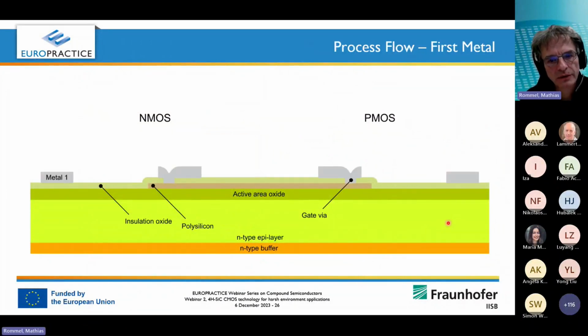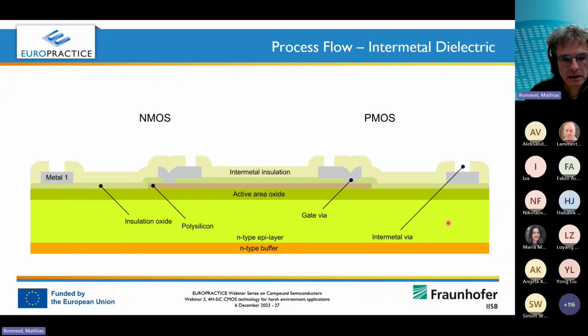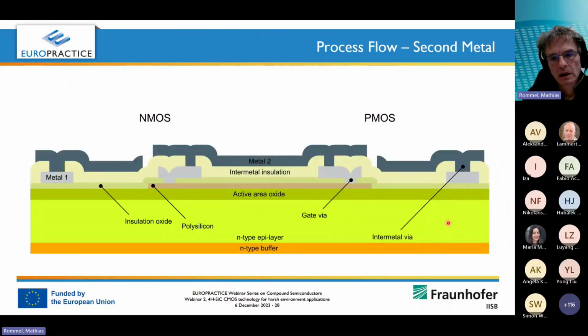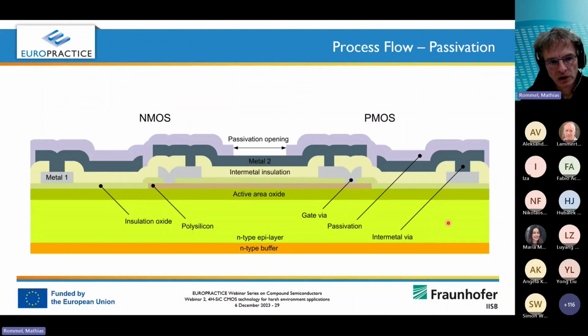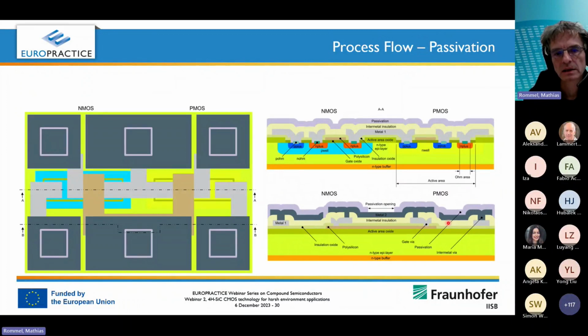After that, we deposit and structure the first metal. And in our case, to achieve high temperature operation, we so far use a platinum-based first and second metallization. Next, intermetal insulation, second metal, and finally a passivation, which of course has to be opened to get access to the metal 2 layer. But that's all a very standard kind of CMOS in terms of the process compared to silicon in the early years. And here again, you have the top view and also the cross section through the, let's say, active transistor area.